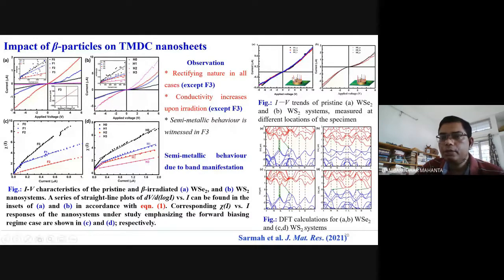So before that we need to check whether your sample is homogeneous or not. For different contact points we have checked, and we found it is quite good, and after that we went for the experiment. Okay, so in case of WSe2 sample, you see for F0, F1, F2 samples, all are showing rectifying nature. So it means it is like a metal semiconductor junction or Schottky junction. However, in case of F3 sample, it was very surprising for us. In this case, we did not get rectifying nature, and we have tried again and again, measured many times for this particular sample, which was irradiated with high dose.